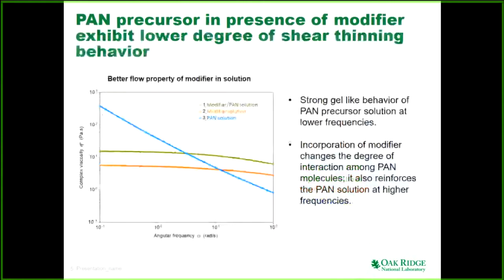So when we use this PAN precursor in existing textile PAN solution, so standard textile precursor, whatever the material is making, and I am adding this rheology modifier, another PAN, separately into the system, let us see what happens to the material's flow characteristics. The blue curve is complex viscosity versus frequency. When you are increasing the shear, the viscosity of the PAN is dropping. And look at the PAN's viscosity. The blue curve viscosity is several orders of magnitude higher than the modifier that we prepared. And look at the shear thinning behavior. As you are increasing the frequency, the material is thinning down dramatically. But that's common in any polymer solution. Whenever you are increasing frequency or shear rate, polymers will disentangle and slide past one another and viscosity will drop.